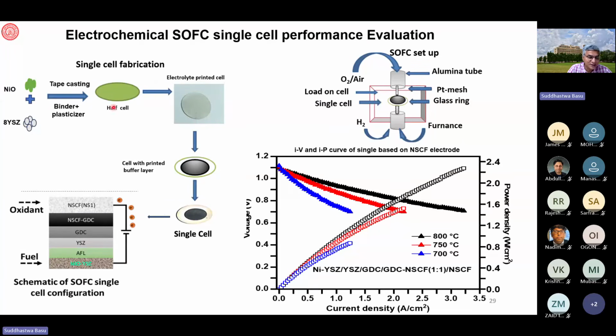Okay, now we made the cell. We make nickel-YSZ as the anode functional layer, YSZ and GDC. This is the electrolyte, so we have the GDC electrolyte, with YSZ to enhance the oxide ion conductivity at the interface. So we have the functional layer. Then we have NSCF-GDC, this kind of mixed material of GDC and NSCF, so that you have both the MIEC conductivity taking place and you have NSCF here.